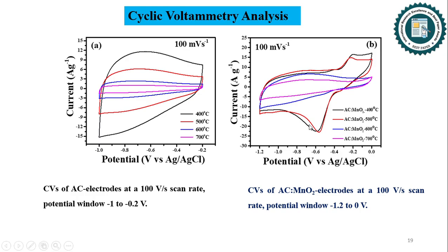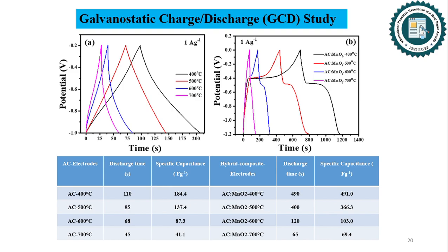Lower carbonization temperatures, that is 400 degrees and 500 degrees centigrade in AC electrodes, resulted in higher specific surface areas and greater charge storage through electrostatic interactions, whereas hybrid composite electrodes displayed pronounced redox peaks from MnO2, indicating reversible Mn3+ to Mn2+ conversion reactions and increased charge storage capacity. Then the capacitive behavior is further investigated by galvanostatic charge discharge at various current densities of 1 to 20 amperes per gram, showing a decrease of discharge time with increase in current density. The galvanostatic charge discharge study compared activated carbon and hybrid composite electrodes at 400 degrees centigrade.